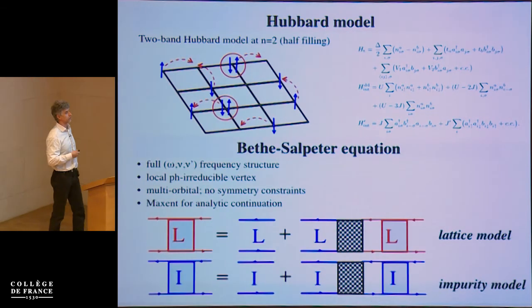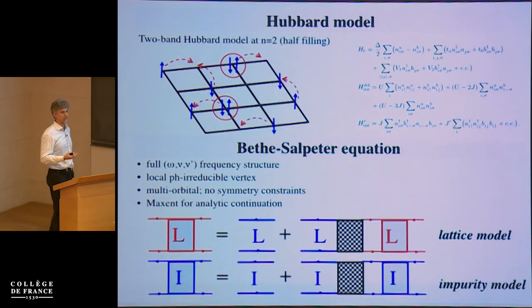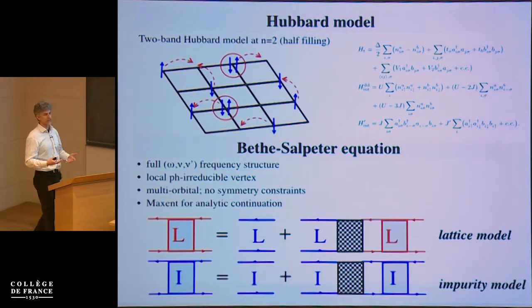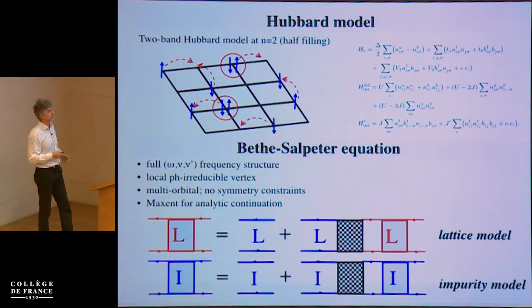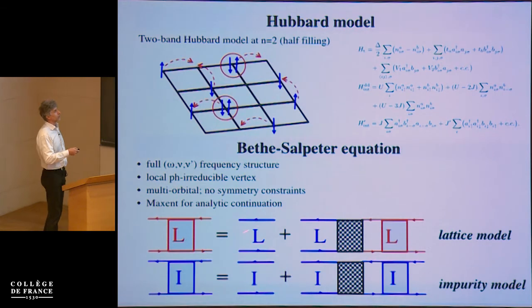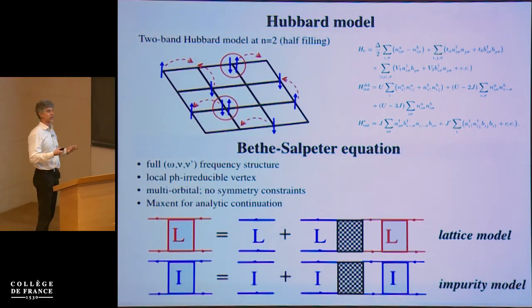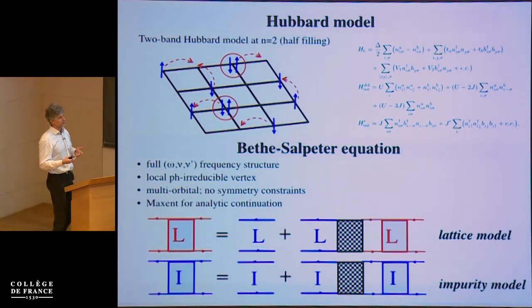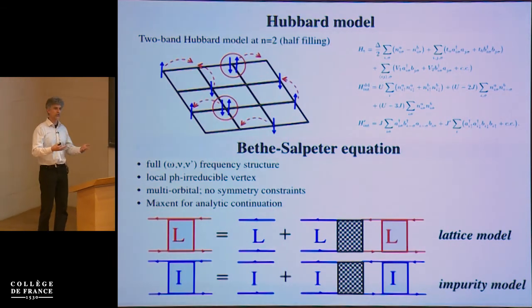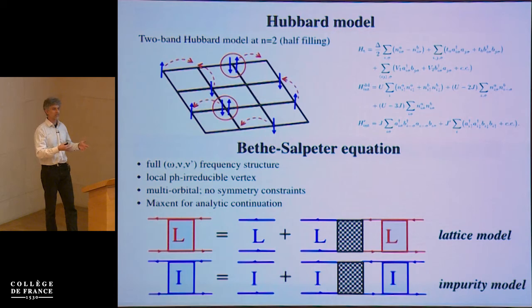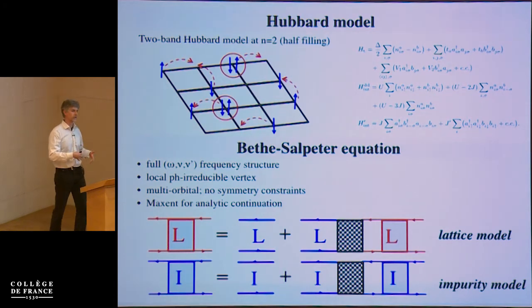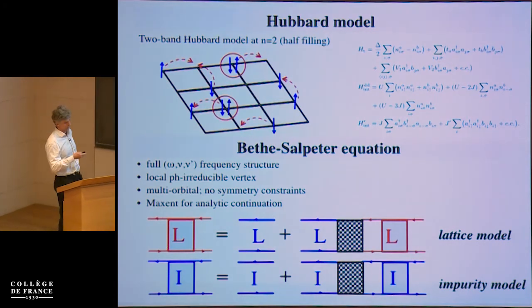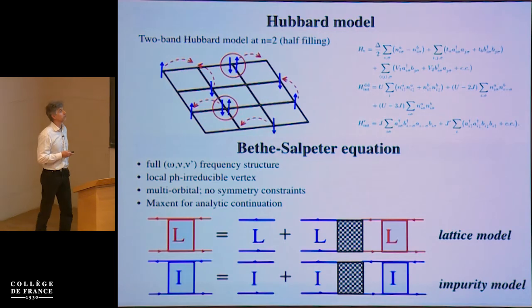I will show you also some results on two particle levels, so basically susceptibilities and dynamical susceptibilities. To calculate these, we have to go to a Bethe-Salpeter formalism. Essentially what you're doing is a kind of post-processing of the DMFT results. You use the converged Weiss field, and with this Weiss field you calculate more complicated correlation functions.